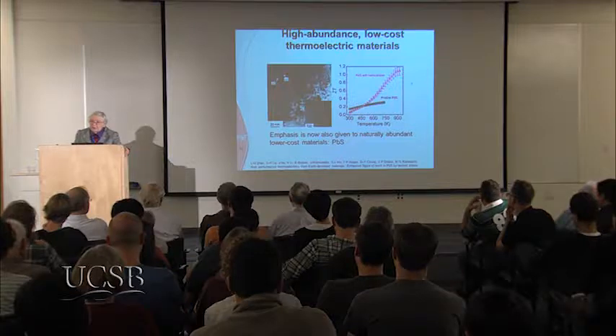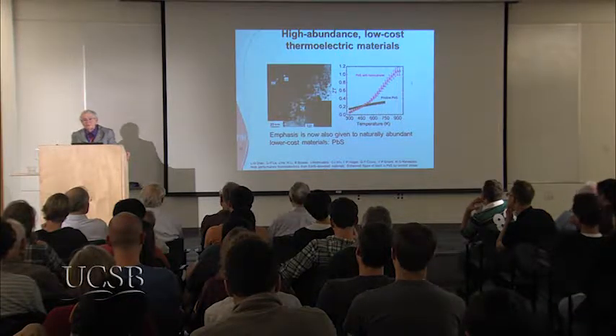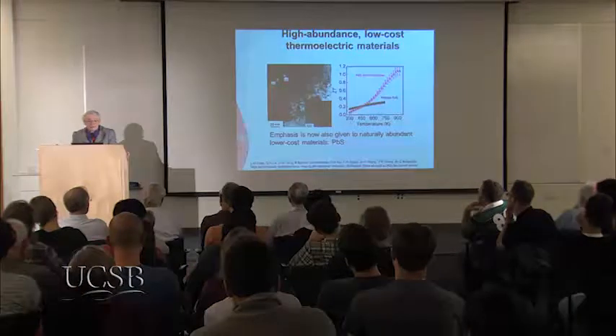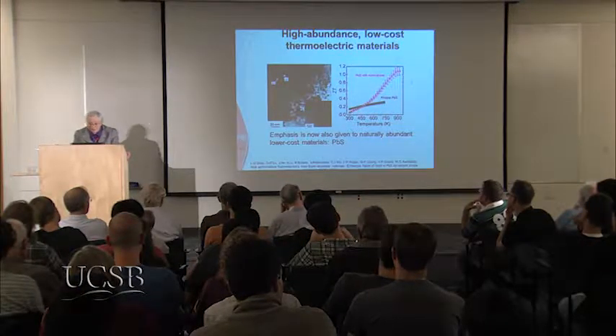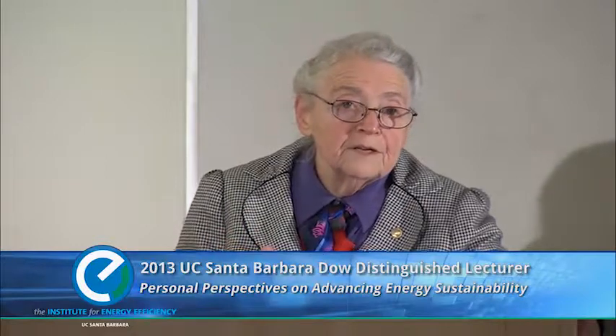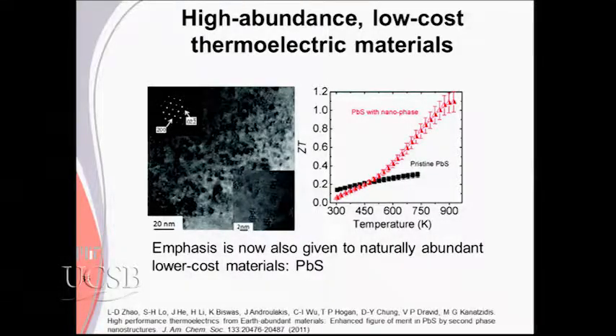So the lead salts are good thermoelectric materials. Lead telluride and lead selenide have been studied very widely for thermoelectricity. Lead sulfide is not yet a very good thermoelectric. So we've been playing around and trying to make it better. But this is just a principle that has to be developed, which is to have a number of common materials. Silicon germanium is a good material. Its germanium part is not so common, but you only need about 5% germanium, and the rest can be silicon. Silicon is quite common, so that might work, but it's only a good thermoelectric at very high temperatures.